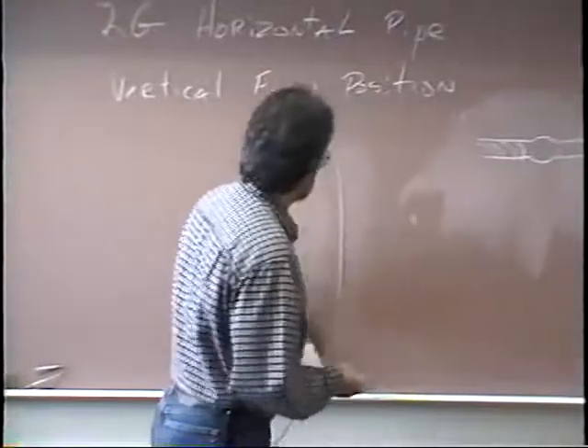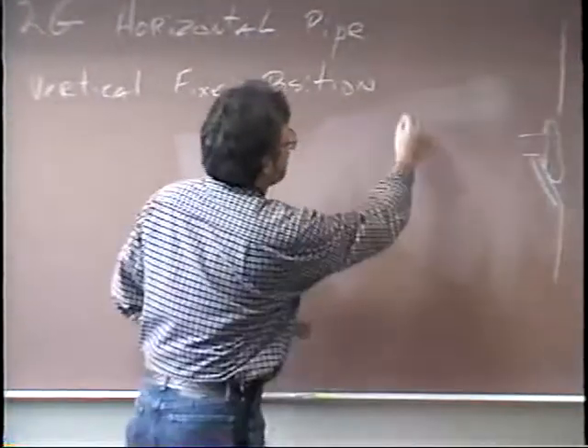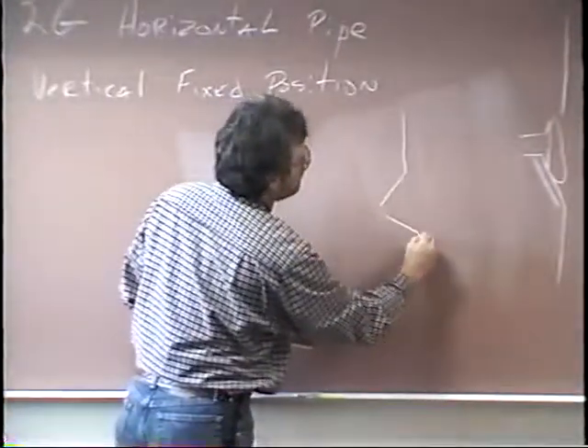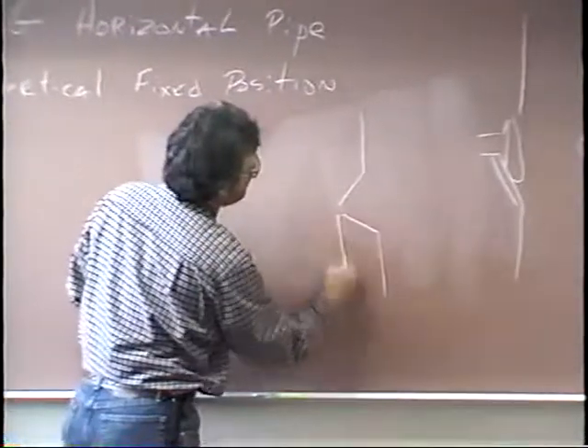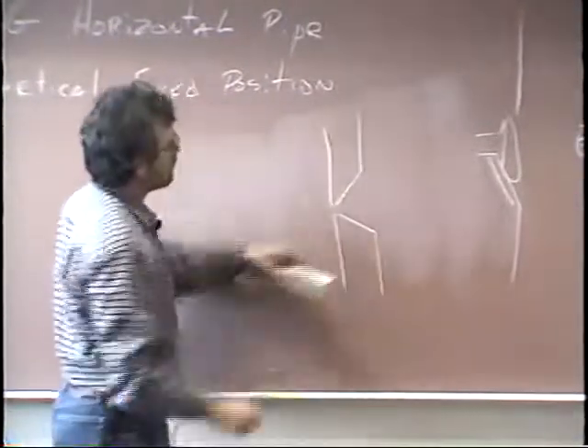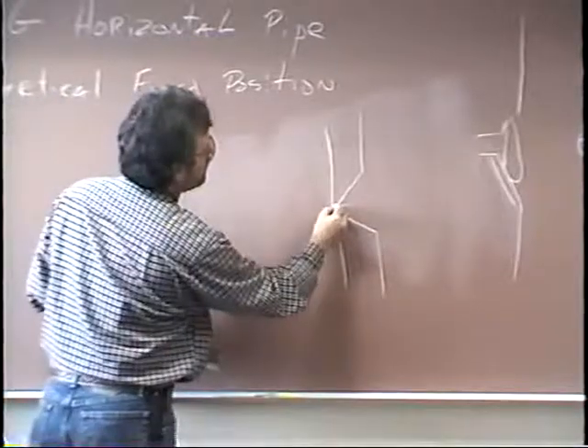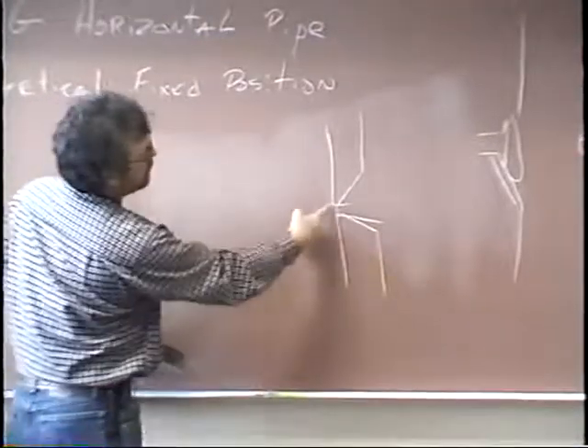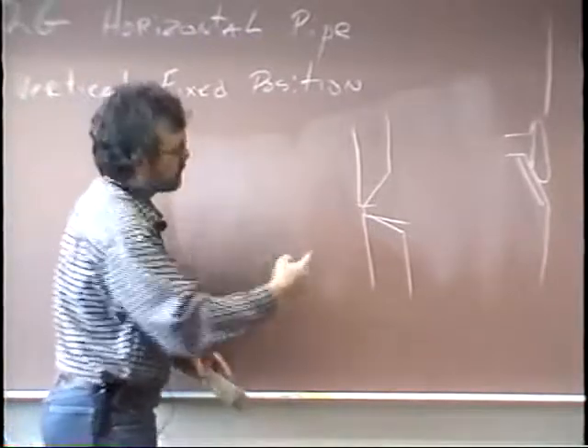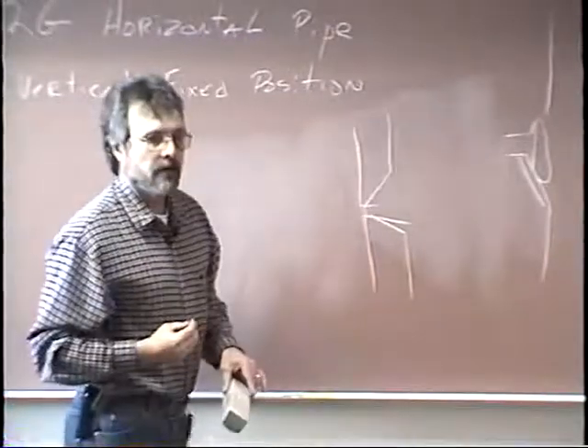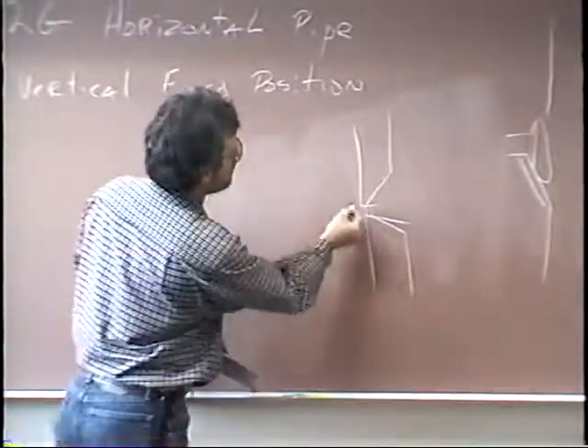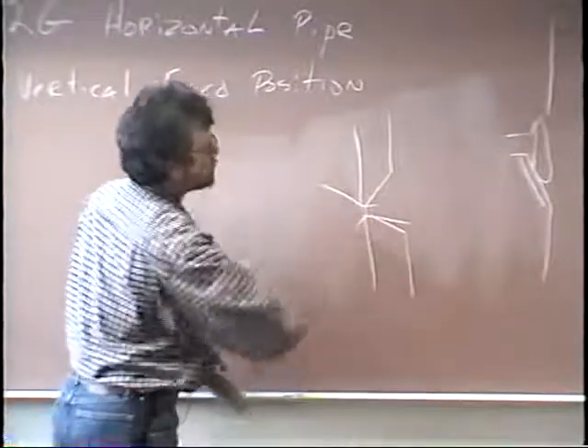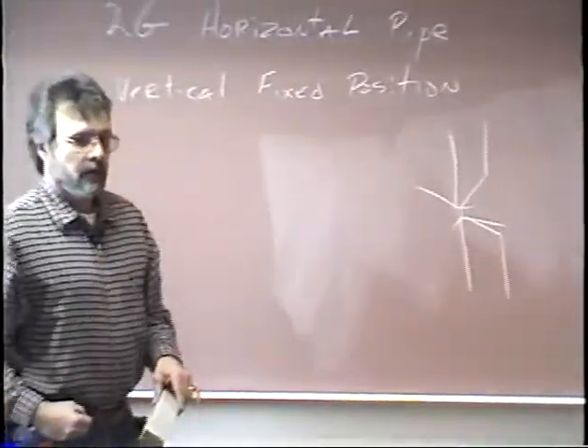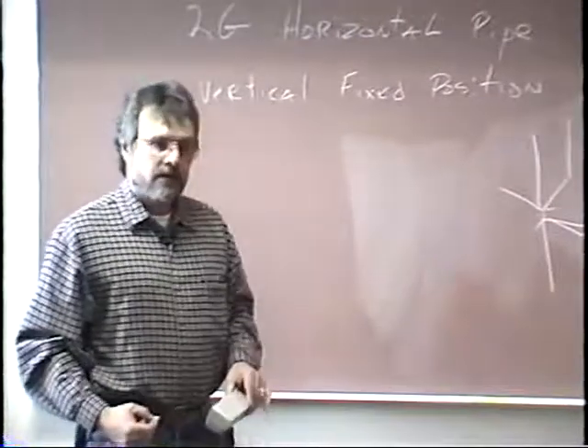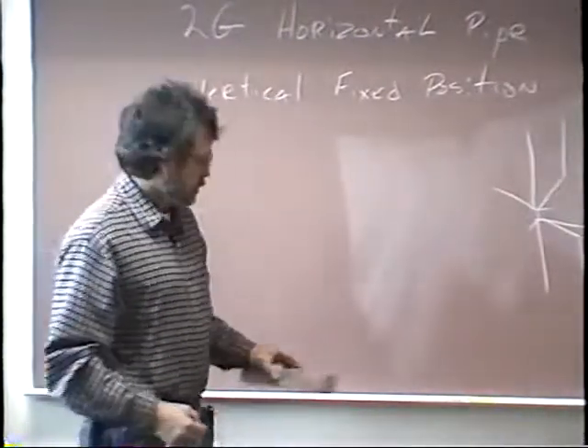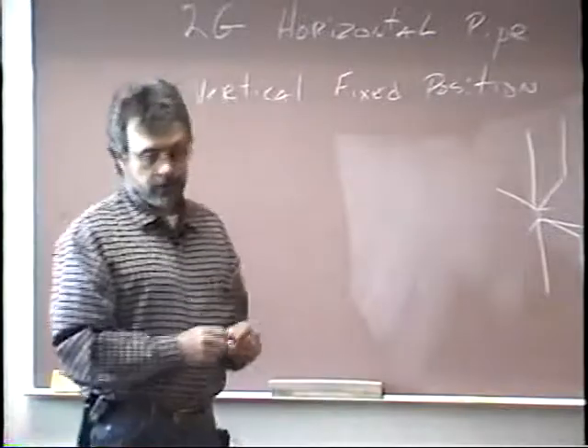Or one other thing that can cause you problems, you've got everything else right. You got yourself a nice little land there and you've taken all your time to get that all fixed up, but then you're shoving the electrode in too far. You've got the electrode shoved in so far that you've gone through half of your land already. You've got it shoved so far into that keyhole, and then the force of the arc is blasting the rest of that land out of there. And you can get an internal undercut by actually shoving that electrode in too far. So those are some of the things that can cause internal undercut you want to be careful of.